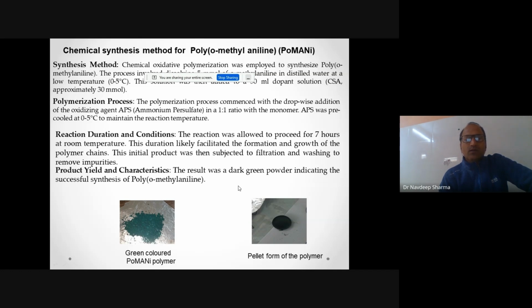After this, we used a mortar and pestle, and we prepared pellets of the polymer with the help of a hydraulic press. These pellets are what we used for further study of the electrical conductivity and the charge transport mechanism of the poly(ortho-methyl aniline) conducting polymers.